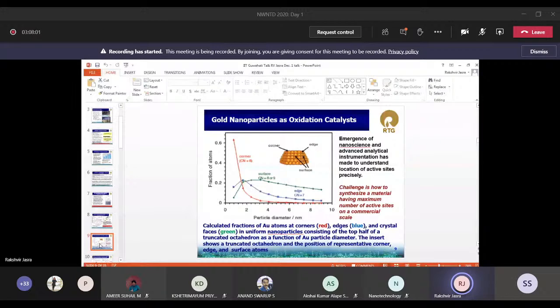But particularly for gold, when you are at less than 10 nanometer, at a size of less than 4 nanometer, then you will see more gold atoms at the corners or the edges. And that is what gives those corner atoms and edge atoms higher activity, because they are not part of the bulk and they are not fully coordinated. So they are active metals, and that has been shown very clearly in this data.